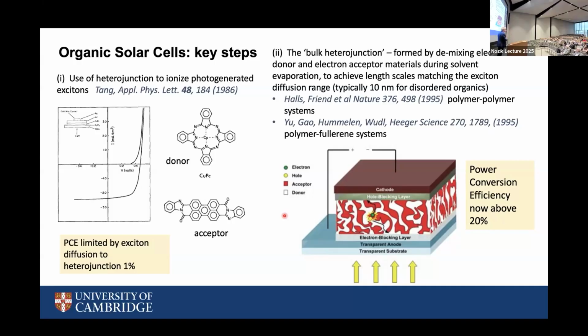There's a cartoon of that on the right. And there are many ways of doing that. The ones that we use with the organics are extraordinarily simple. We mix together a donor material and acceptor material with a solvent, and if everything works magically well, it self-organizes to form this nanostructure where the key is that light's absorbed close enough to the heterojunction that you'll always get the charges generated.